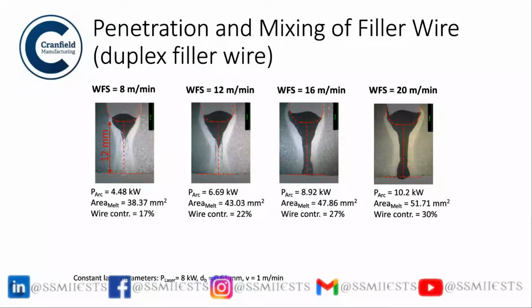So filler wire. In this particular study, we have used a duplex filler wire just to have chromium as a signature element to see how much it penetrates. So I know that it will be cracking and the weld will not be looking very good, but still we did it because otherwise it is very difficult to accurately quantify the mixing.